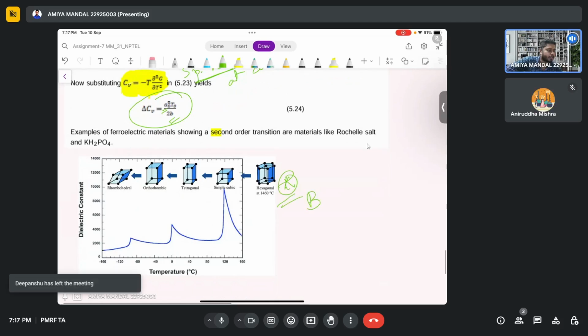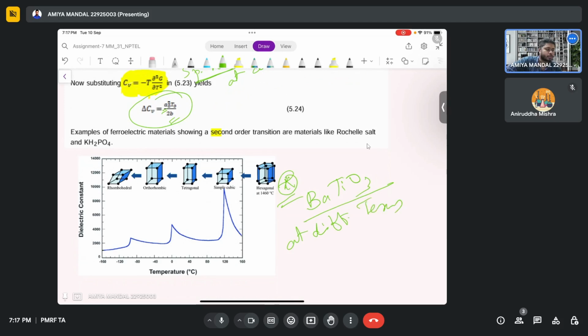And this is a diagram of barium titanate at different temperatures. Just see the regions of temperature. This is one region of temperature. This is another region of temperature. This is yet another region of temperature. So in this region, from minus 160 degrees to minus 100 degrees, you can see it shows a rhombohedral phase.